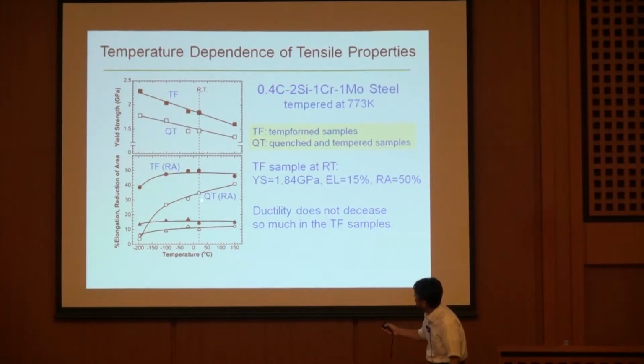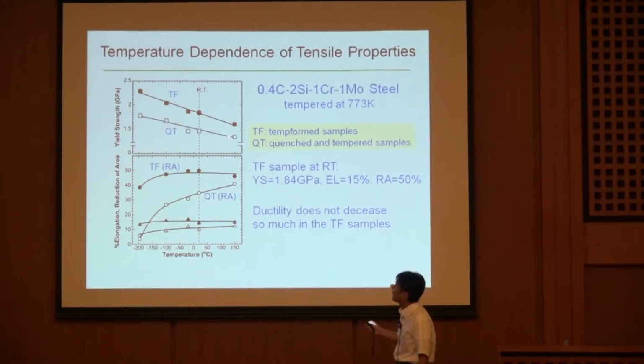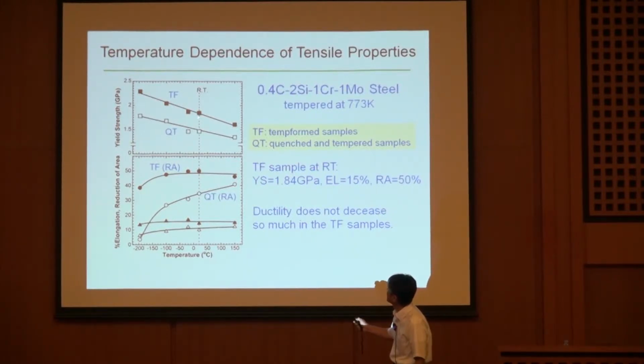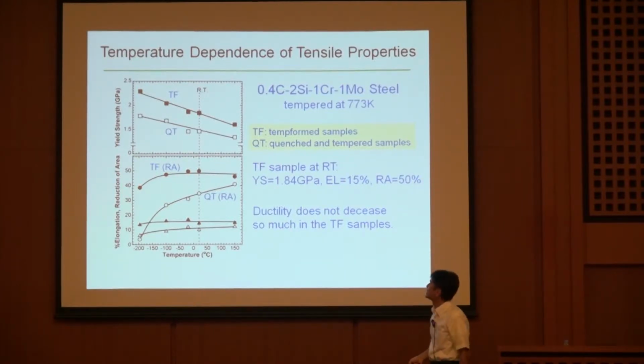This is room temperature. This is testing temperature. So, BCC steel shows an increase in yield strength as the temperature decreases, like this. QT sample is here, and TF is the temp-formed sample. The ultrafine elongated grain structure has a higher strength level, but the temperature dependence, I can say, is similar for both types of steels.